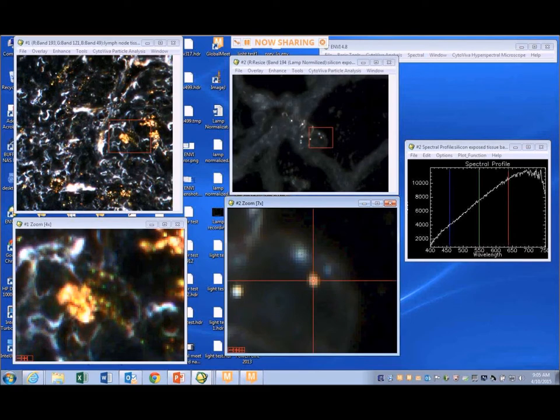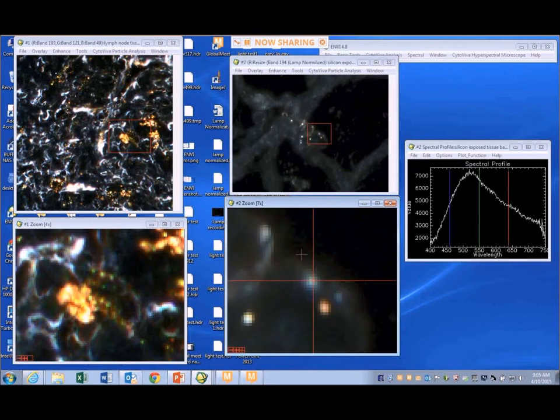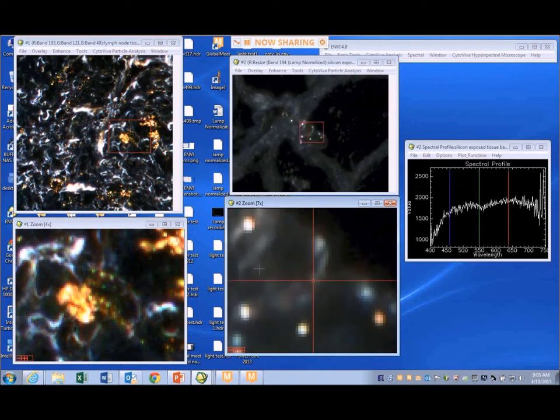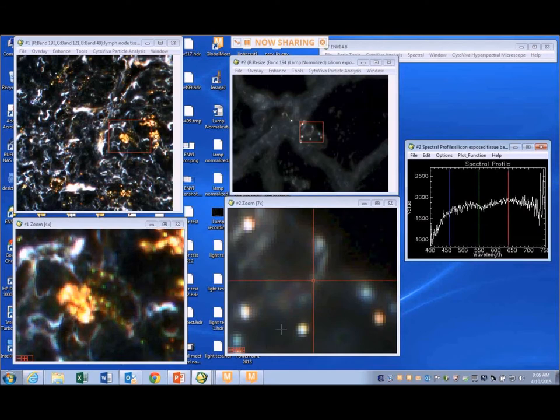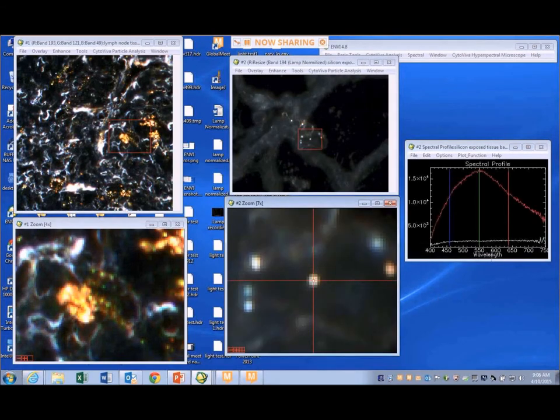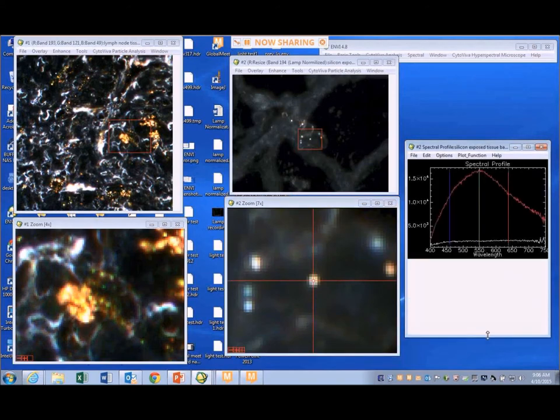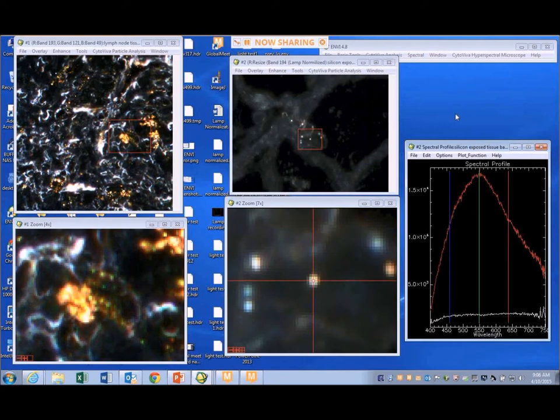One thing this technique allows you to do is understand how the material — in this case silica particles — as they interact with tissue, the tissue has a way of changing the spectral response. As Leslie clicks onto an area of tissue containing no nanoparticles, you see a dramatic change in the spectrum. She's now collecting the spectrum of tissue, and now the spectrum of the silica particle, allowing you to clearly see the dramatic difference. Silica in its reflectivity in the microscope is dramatically more bright and intense than the tissue itself — especially in this case, lung tissue, which is very porous, and this is probably about a five micron slice.